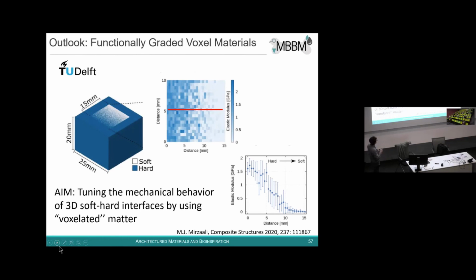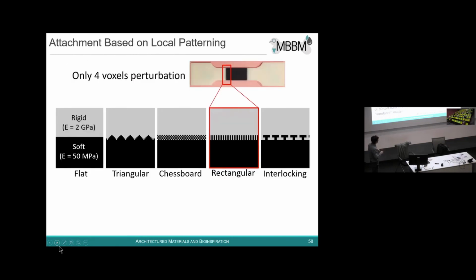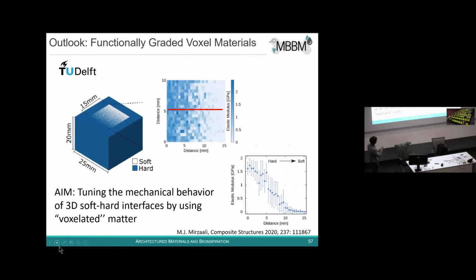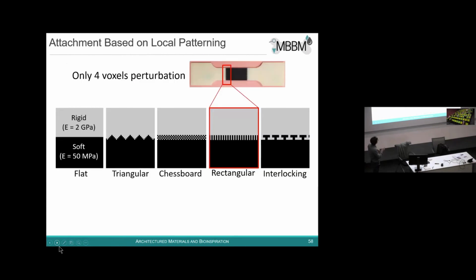So this is something that we are doing more at the length scale of several millimeters. And at the smaller length scale, of only some tens or hundreds of micrometers, instead of a large perturbation, a long gradient, we are introducing a very small perturbation. We just perturb the interface between a rigid material and a soft material by changing only 4 voxels. This is defined as minimal surface patterning, or interface patterning. And we introduce different designs, different patterns between soft and hard voxels, to see the corresponding failure behavior. So these are 2 different things that we are exploring.